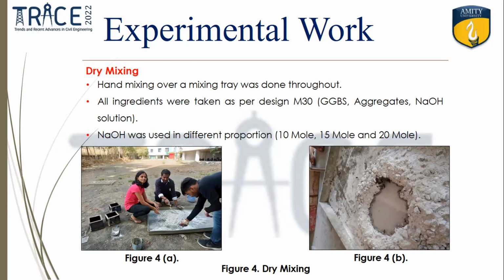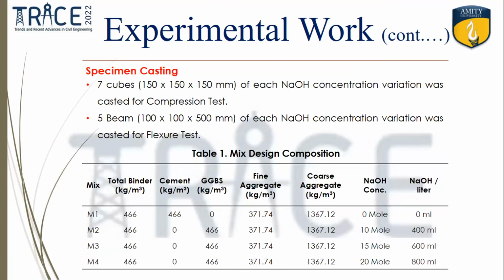The different thing which I performed was that none of the researchers have previously used 100% GGBS, so I used it as a 100% replacement, and that too with these 3 concentrations. These were the casting specifications. I casted 7 cubes of each mix. You can see in the table, mix 1 stands for the conventional concrete, which has cement, 0 GGBS, and 0 NaOH. Whereas in M2, M3, and M4, we have 100% replacement of cement with GGBS, and also, according to the molarity, the volume of NaOH.